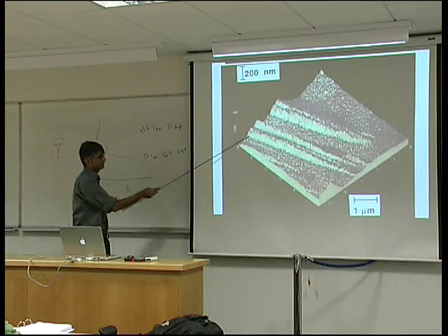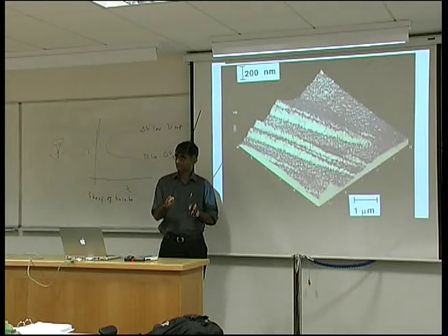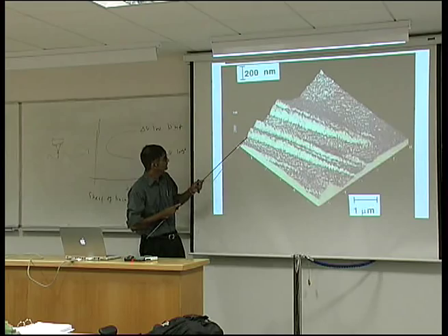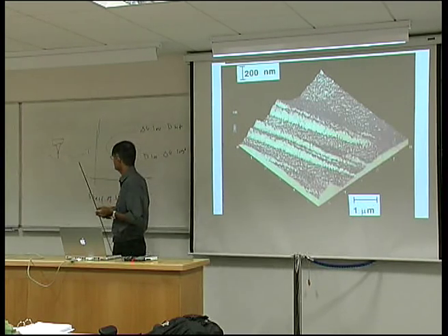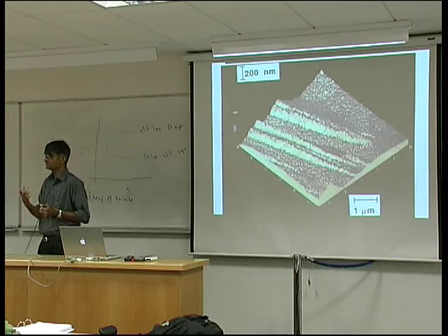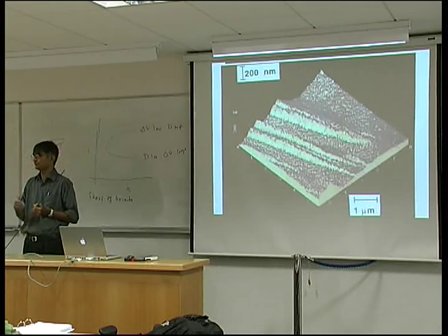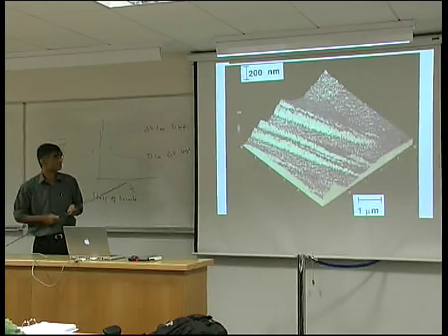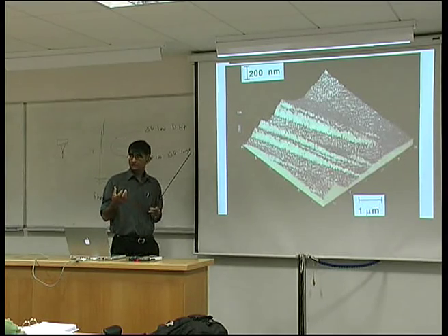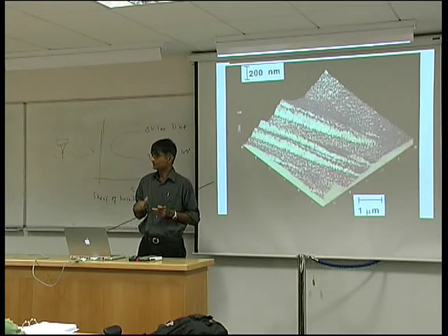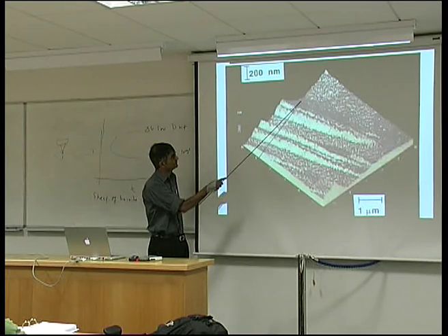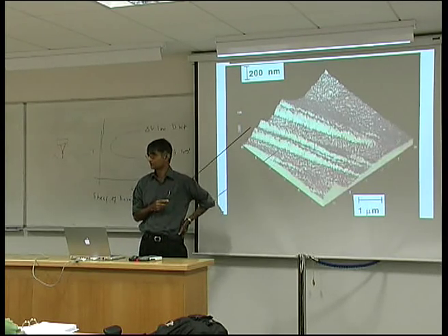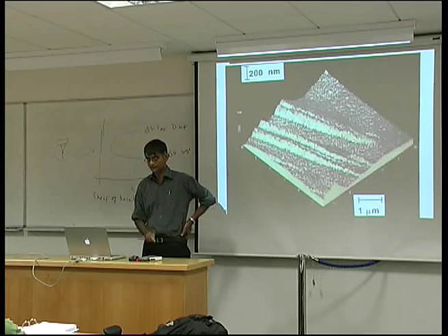Now clearly this is a shear deformation. If you follow this, you can see that's a shear deformation. You measure it, the shear strain is the same as we observe with martensite, of the order of 0.26. Now there is another interesting feature that you can see here, and that is this part here. There is plastic relaxation of the austenite adjacent to the plate.